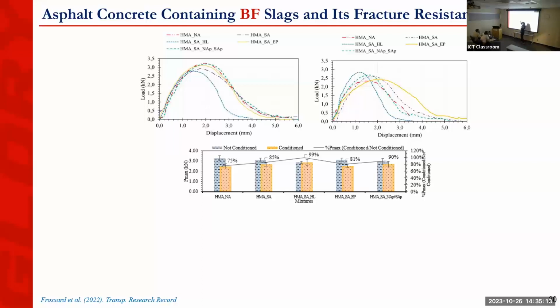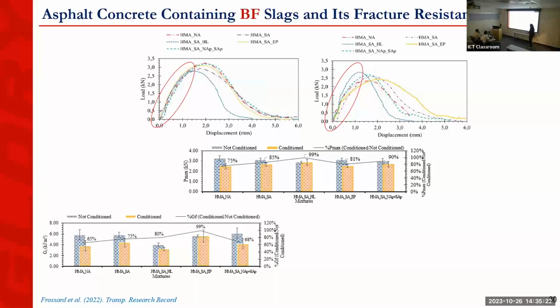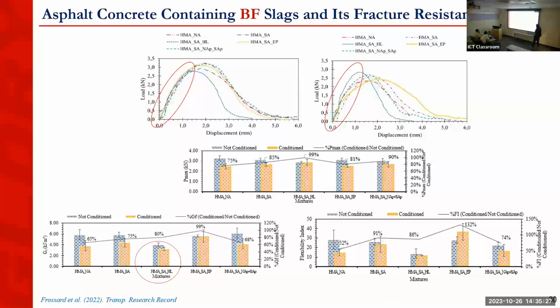If we just look at the maximum force, they have almost the same ranking order as the TSR values. But when we look into the fracture energy and the flexibility index, you can really see a difference depending on the filler that you add, the chemical composition of the filler. By inducing moisture damage, you can really differentiate the contribution of each filler to the adhesion resistance and, as a consequence, the resistance to fracture. Hydrated lime has the lowest flexibility index, and we attribute that to hydrated lime enhancing rigidity: the mixture becomes stiffer, and in that way cracks propagate faster. The EP powder did not increase the stiffness too much, but it still improved the adhesion, so in that way we improved the flexibility index.